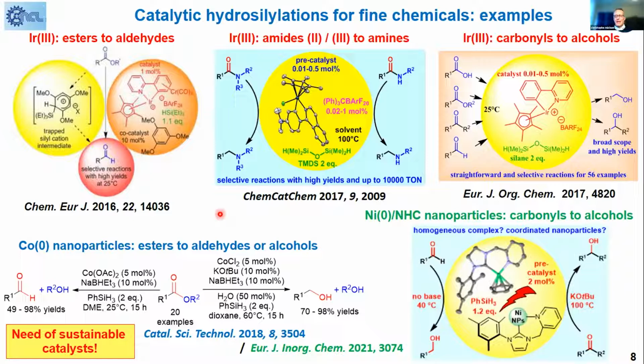So we switched then to nanoparticles of cobalt and nickel, which are much more abundant metals, focusing mainly on nanoparticle catalysis. First we developed cobalt zero nanoparticles for the selective conversion of esters to aldehydes or ketones or alcohols, depending on the preparation of the catalyst. This was ligand-free catalysis, and we could observe evidence of the presence of cobalt nanoparticles in both systems. And more recently, this year, we published a system of nickel zero nanoparticles stabilized by NHC ligands, diaminocarbene ligands. This catalyst could be applied for the reduction of ketones and carbonyl derivatives.